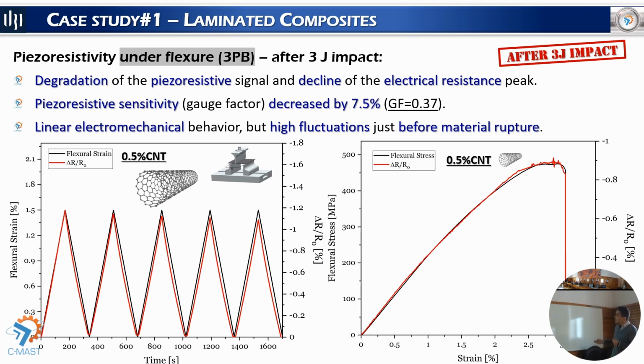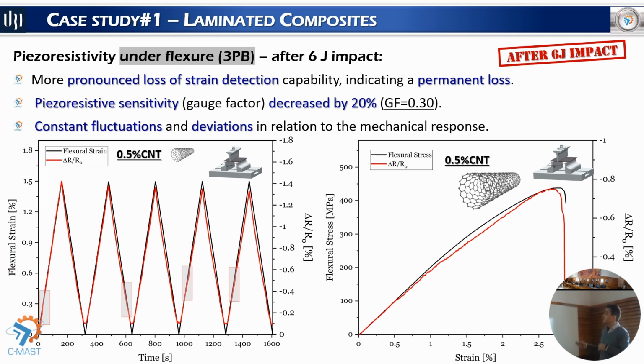In the monotonic test, until the rupture, we can see the same. The noise at the end of the experiment is even bigger than it was in the case of the original sample before the impact tests. We study the same after 6 joule impact tests.